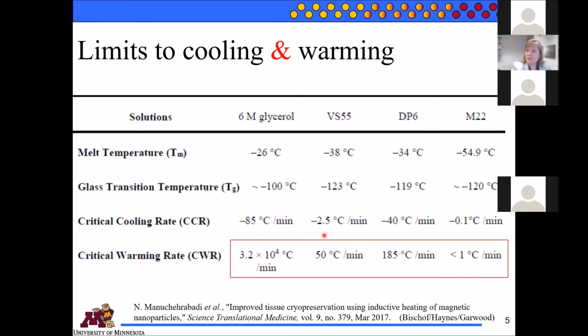But if you can uniformly freeze, like this VS55 is the one I'll be showing you results on, at minus 2.5 degrees per minute, you can have a pretty uniformly frozen tissue. And the key, as I said, is to increase the concentration of the VS55 as you're cooling. Now you have this frozen tissue in the middle of VS55, and you need to heat that uniformly at greater than 50 degrees per minute if you want to be able to avoid crystallization.